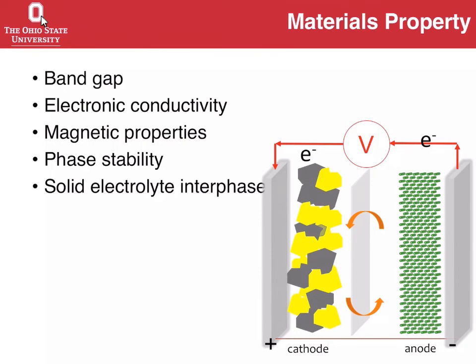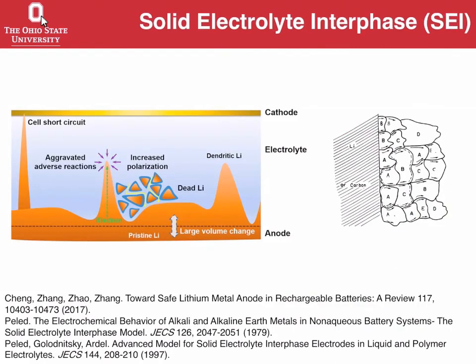And also, if you haven't heard of this term yet, the solid electrolyte interphase, it is both the bane of your existence and the reason why batteries work at the same time. Okay? These interfaces right here, what typically forms when these batteries are being cycled, if you haven't already learned this from Professor Meyer's class that's concurrent to our lab, is you have your cathode, you have your anode, and you have your separator. This plastic separator is drenched in an electrolyte, which is a salt in a solvent, right? So this electrolyte you'll be using is commercial 1 molar LiPF6 in ethylene carbonate dimethyl carbonate. Okay, so you can imagine this salt being highly corrosive, reacting with lithium, as well as reacting with your lithium cobalt oxide or whatever lithium transition metal oxide that you choose.